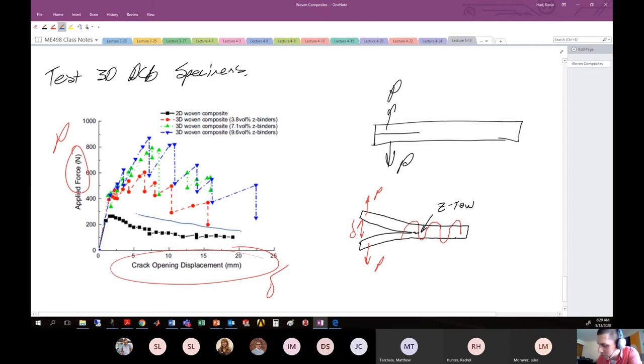All right, so we see this first black line here. This is just a 2D woven composite. All right, there are no Z-toes in this guy. And we have the typical steady, stable crack propagation that you might envision for a 2D woven composite. Okay, so we load up, we first start to get some crack opening, and then we're steadily opening the crack as we go. Nothing too exciting. You did the analysis on this for problem number 2 of your fracture mechanics homework, so you're all experts now, right? Right.